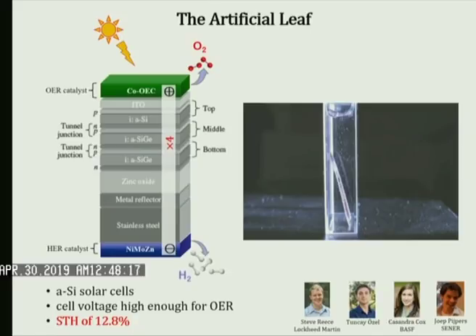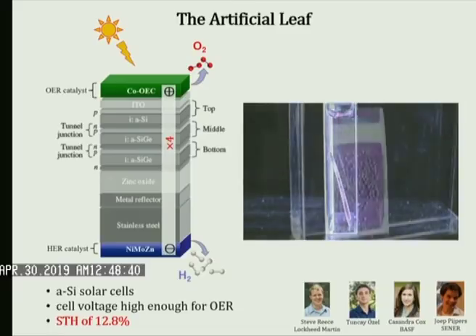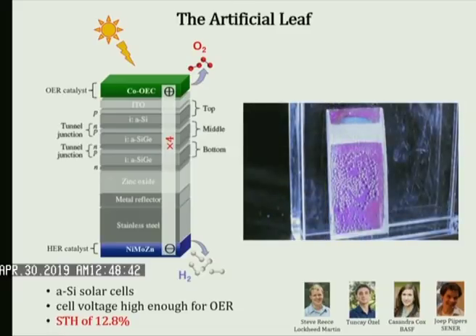And when the nickel hydrogen catalyst gets charged up, hydrogen comes out. And now I'm not plugging it into the wall. I'm just using the sun. And it really works. So that's a wafer. The silicon's around 100 microns of silicon. And then it has a thin layer of coating of the catalyst on each side.